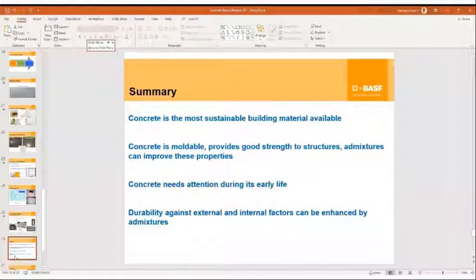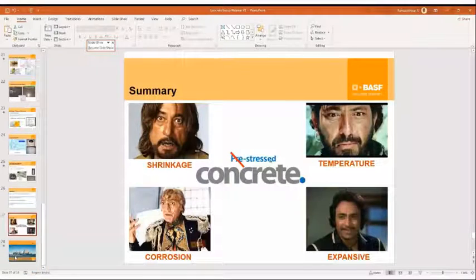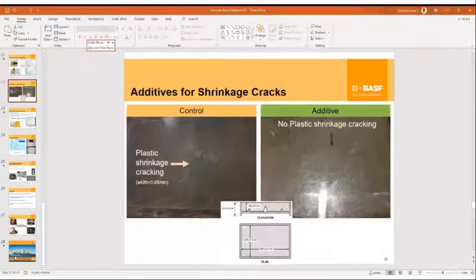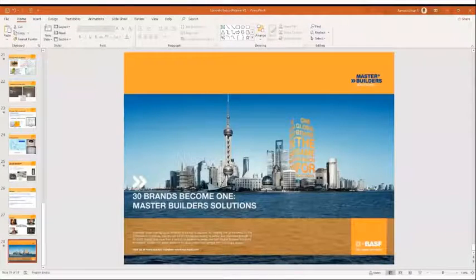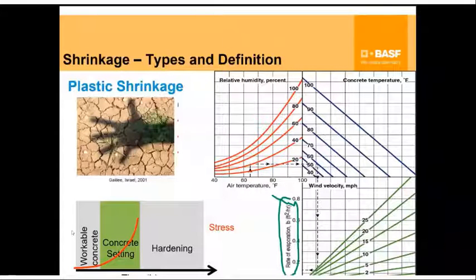As the concrete starts to set, it becomes harder, right? Then the flexibility is lost quite considerably, and that is when your plastic shrinkage property becomes very significant. But just because something has plastic shrinkage doesn't mean that you're going to get cracks. All materials have plastic shrinkage. You cannot stop it because the water has to go out.